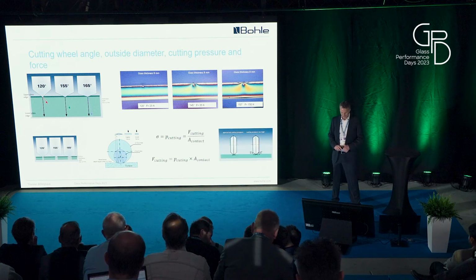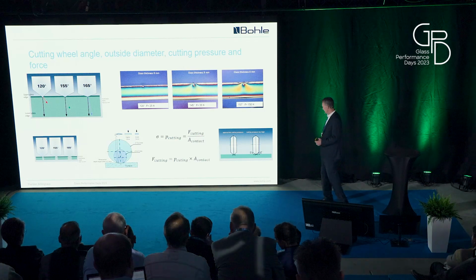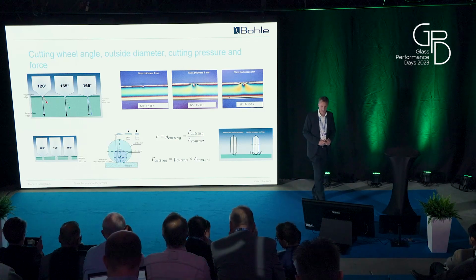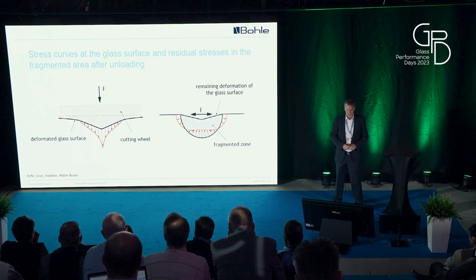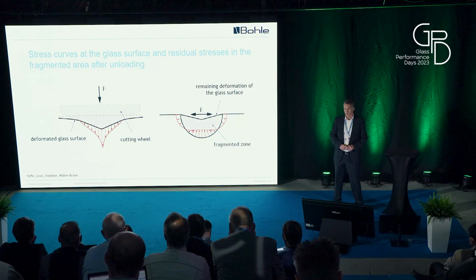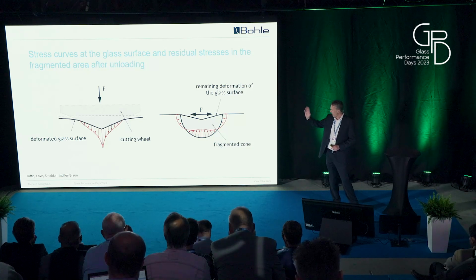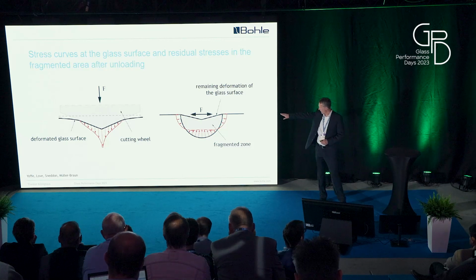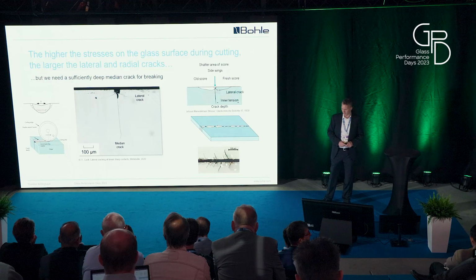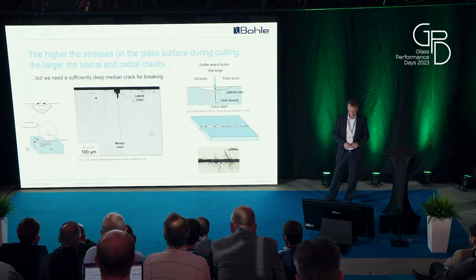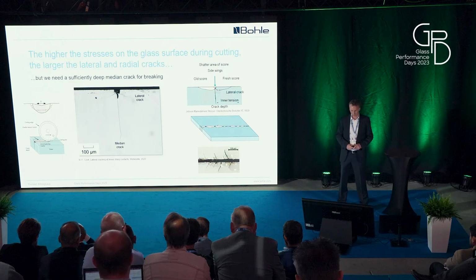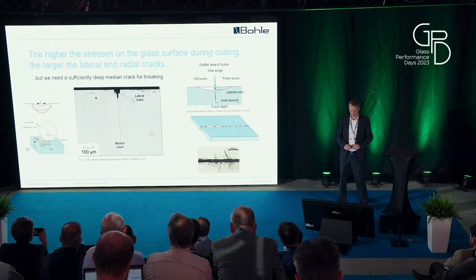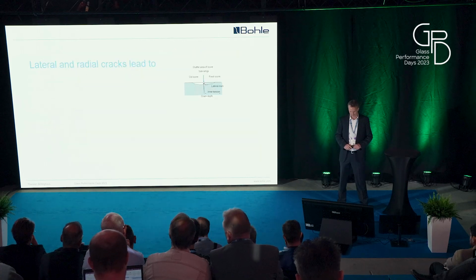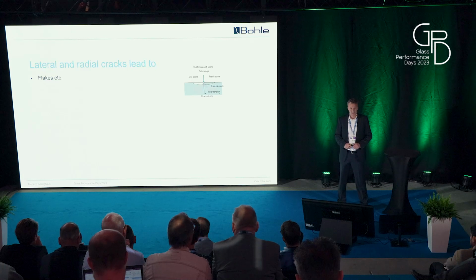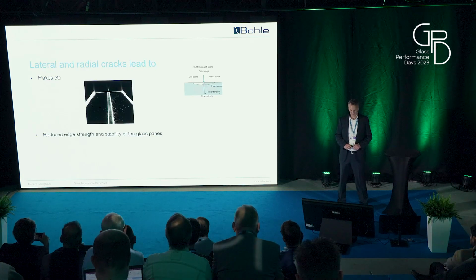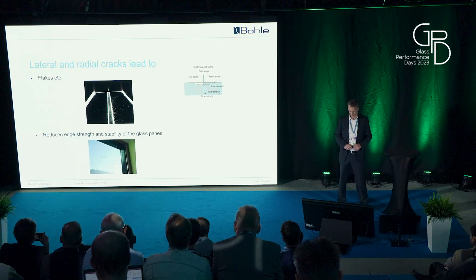So this is an important thing to keep in mind, because if the pressure at the surface is too high, you will get splinters and damage your glass. Why is this so? If your cutting wheel touches the glass, you bring in the stresses. And if you relieve it when the cutting wheel has passed by, then you will also get lateral residual stresses that later on lead to lateral cracks that you don't want. So we don't want the shattered zone, and we don't want the lateral crack. The only thing we need is the median crack and the tensions you bring to the glass. Because if the pressure is too high on the surface, you will get flakes and a reduced edge strength stability of the glass panes.